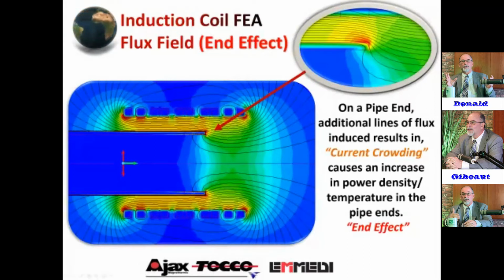And this condition is prevalent when you're in a heat treat line, when you're feeding the pipes; you must keep them butted together. Now that doesn't mean they're 100%. We've done a lot of analysis and shown we can live with some gap, and the field will cross over. But we're talking a max of a half inch; that is stretching the envelope here.